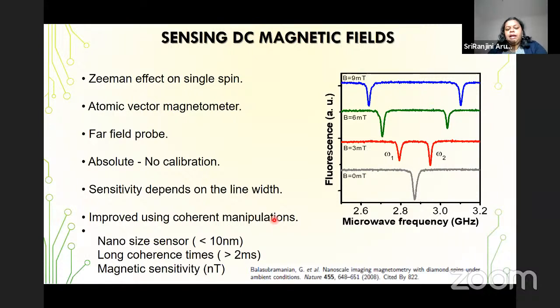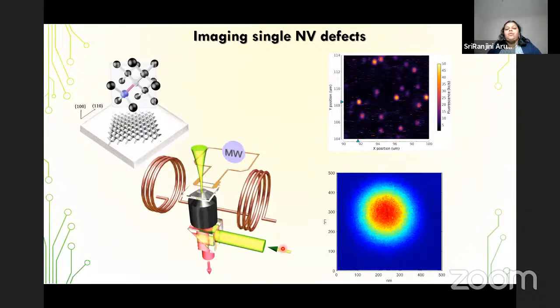So they are typically nano-size sensors, less than 10 nanometer, and it is atomic because it is just a nitrogen and a vacant site, with a long coherence time, more than 2 millisecond, and very high magnetic sensitivity from microtesla to nanotesla. So how do we image such NV defects?